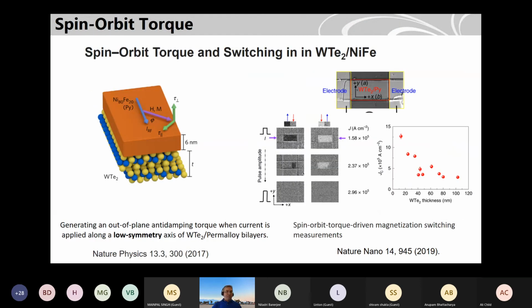And this material has been quite popular, because the spin orbit torque type of experiments I showed are not very convenient for a perpendicular magnet, while for high density integration you need to integrate a perpendicular magnet for spin orbit torque. So the magnet you use should have perpendicular magnetic anisotropy. And to switch a perpendicular magnetic anisotropy system, you need an out of plane anti-damping torque, which means an out of plane spin polarization. And because tungsten telluride, as I told you earlier, gives an out of plane spin polarization, that is quite good. Such a system was not known before; this is just after tungsten telluride came.